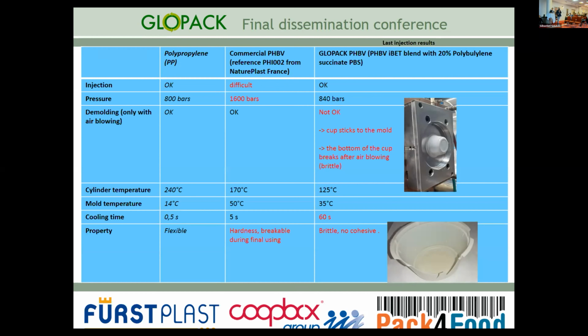Polypropylene injection is easy. Pressure is correct, not too high. The demolding is easy with air. We inject with a cylinder temperature of 240 degrees and the cold mold. And the cooling time is very short. And finally, the packaging is flexible.